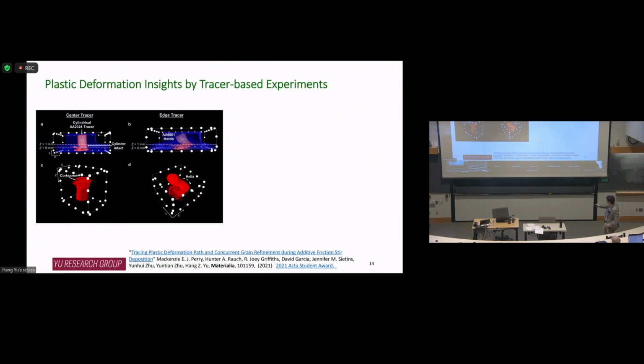So the red and the purple basically show you the tracer material. That is my 2024 aluminum. And in this case, the blue, and in this case, the transparent area, that's my base material, 6061. I don't care about that part. I care about my tracer. So you see the tracer starts to develop this helical shape during the deposition, which is expected because you have downward feeding, you have rotation as well, and there is a rotation gradient between the top and the bottom of the deposit layers.